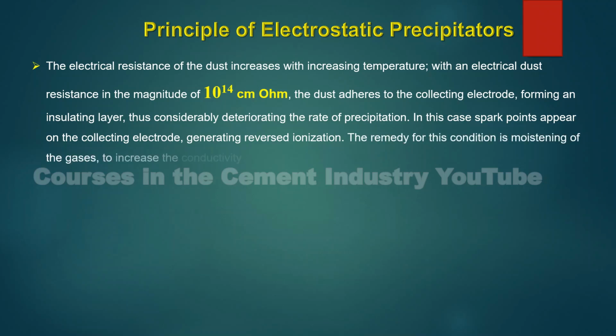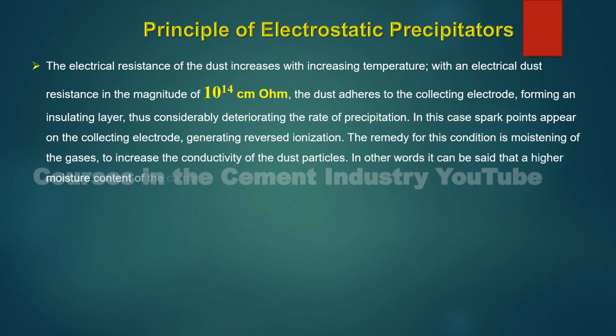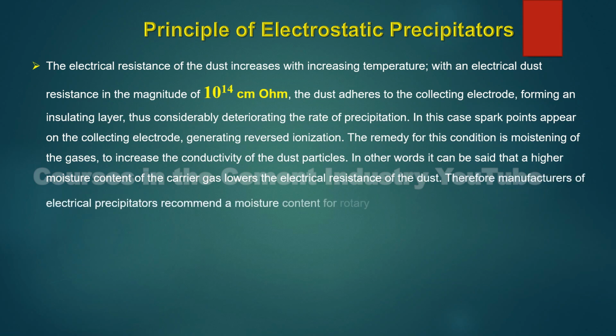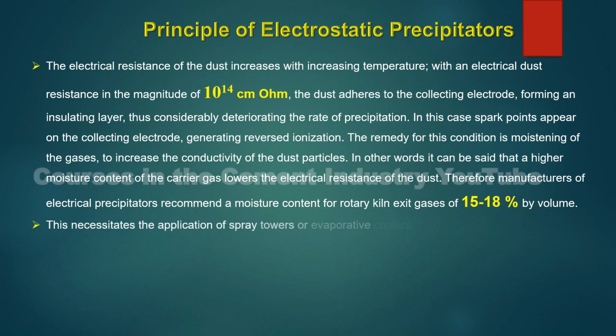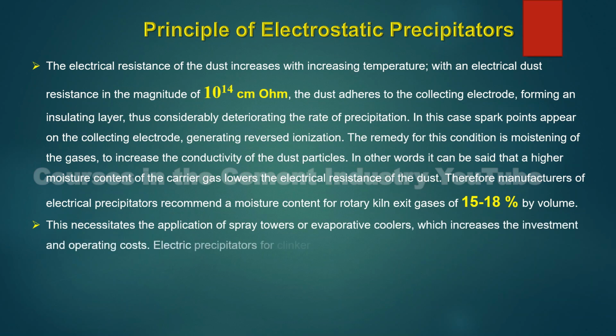The remedy for this condition is moistening of the gases, to increase the conductivity of the dust particles. In other words, it can be said that a higher moisture content of the carrier gas lowers the electrical resistance of the dust. Therefore, manufacturers of electrical precipitators recommend a moisture content for rotary kiln exit gases of 15 to 18% by volume. This necessitates the application of spray towers, or evaporative coolers, which increases the investment and operating costs.